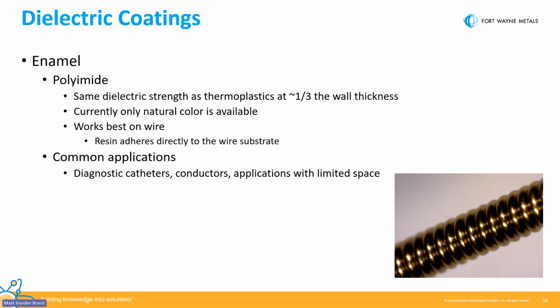Outside of extrudable coatings under that dielectric umbrella are enamel coatings. And what we find is that the most widely used enamel coating for dielectric performance in med device happens to be polyimide. Polyimide has an extremely high performing dielectric strength compared to any of the fluoropolymers. In fact, it's roughly 3 to 4 times as strong. We said that many of the fluoropolymers were around 1500 to 1800 volts per mil. You can get that same dielectric performance at about a third the wall thickness. So roughly a third of a mil, you can get that 1800 to 2000 volt performance out of a polyimide.